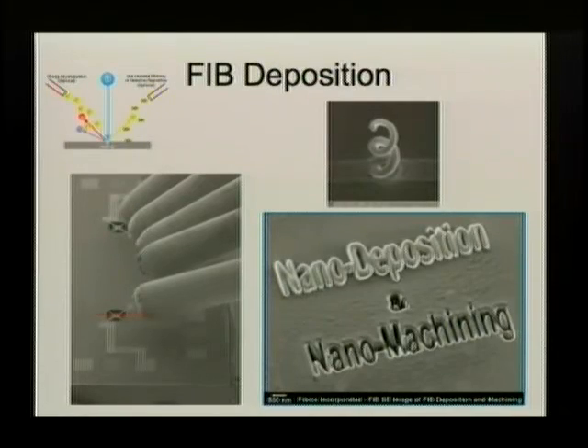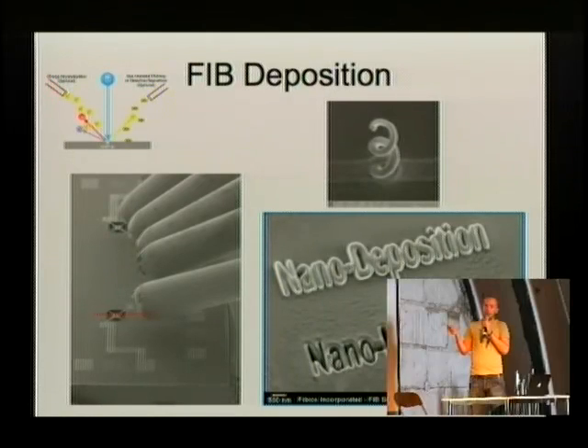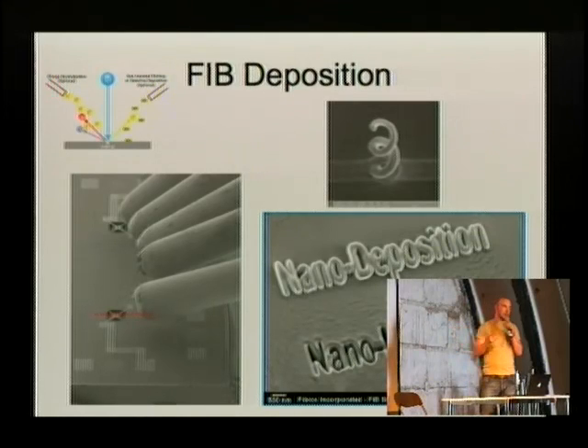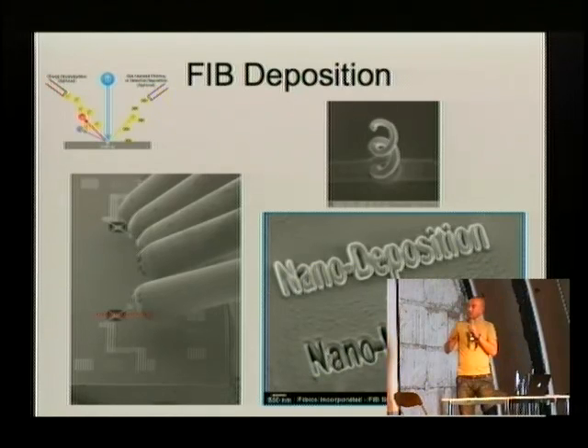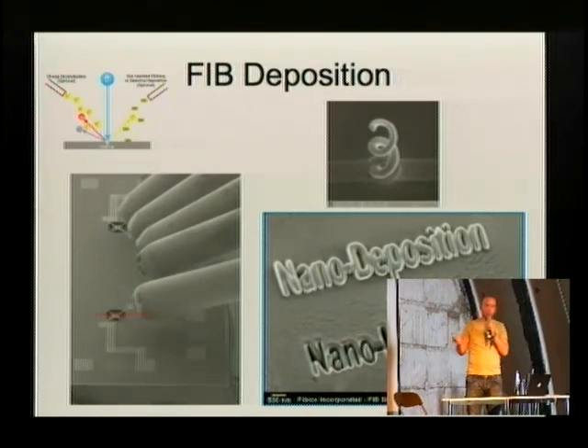There's another thing we can do with the FIB, and that makes it even more interesting than the milling. If we inject some gas into the chamber with a small needle, normally you use some sort of carbon compounds that bind to a metal or an insulator, you can deposit the material onto the surface. So the chemical bonds inside these carbon compounds get broken up by the ion beam, and you can locally deposit